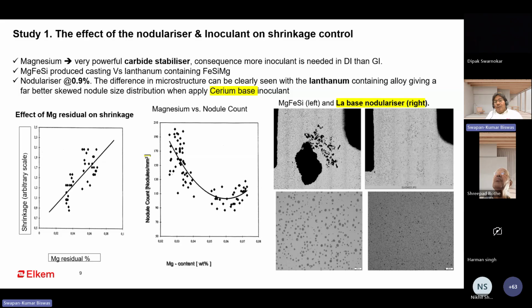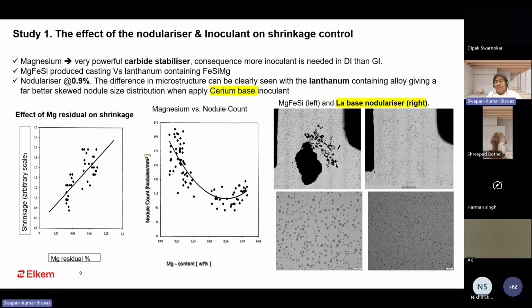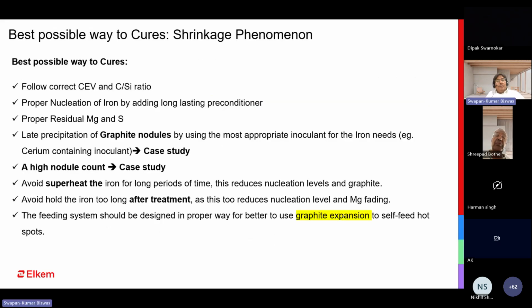So when your nodule count and nodularity increase, you are able to eliminate micro shrinkage or micro porosity. With the help of better ferrosilicon magnesium and cerium based inoculant, it helps to minimize or even achieve 100% elimination of shrinkage defect. So the best possible way to cure this shrinkage is to follow the correct carbon equivalent and carbon silicon ratio.